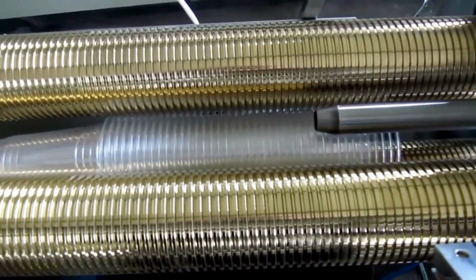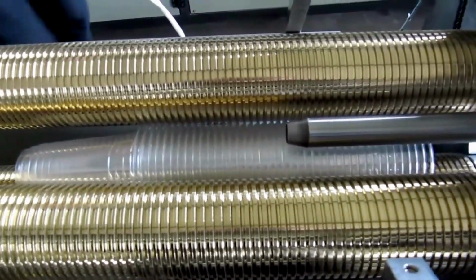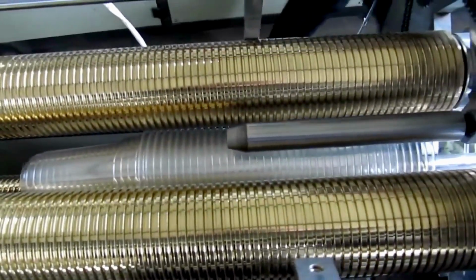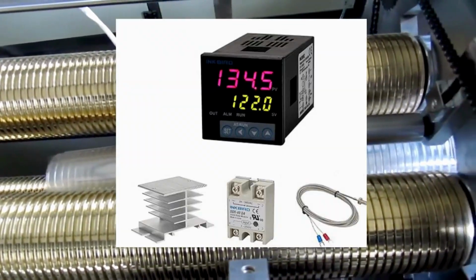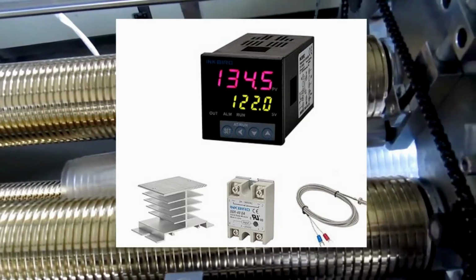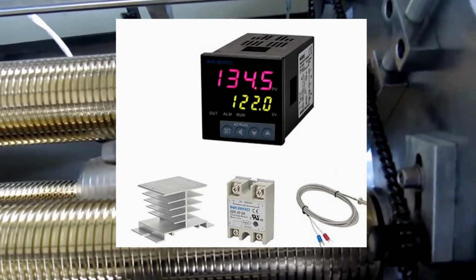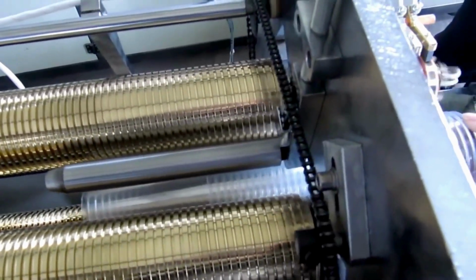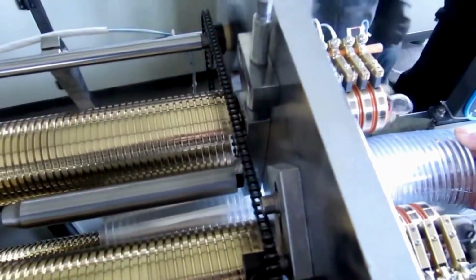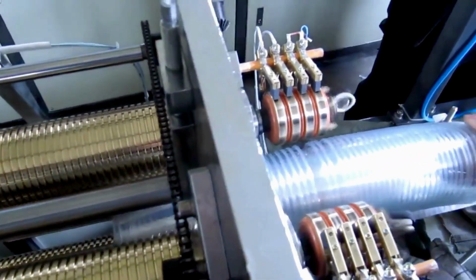Temperature control here is critical. Too cool and the rim cracks, too hot and it loses shape. That's why modern systems use PID-controlled heaters to keep the temperature within just a few degrees of TG. After rolling, the cup is cooled again using forced air or chilled mandrels to lock in the final shape.